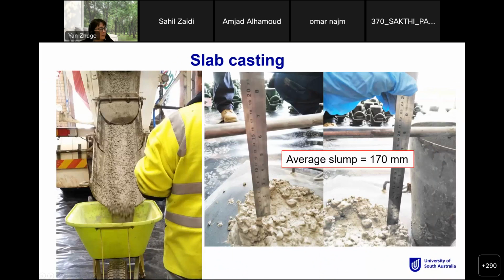Okay. So some more results, you see that is the pouring of concrete slabs. So it's very interesting actually. In our small laboratory testing, we found out that the average slump was quite small. It's pretty sticky. The workability is not really good for the crumb rubber concrete. So we used a higher percentage of the rubber. But with the same mix design for the real construction, it gave us a different story. So actually there's no workability problem at all. And the average slump was more than our calculations. It reached about 170 mm, much more than what we were expecting. So that's an interesting difference from the laboratory to the real construction.